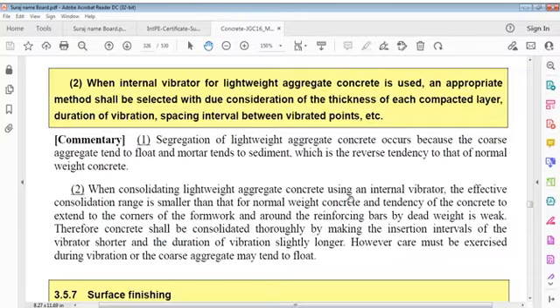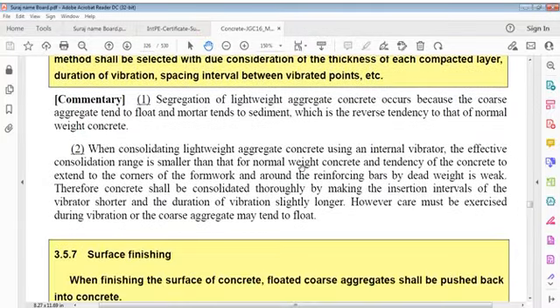When an internal vibrator for lightweight aggregate concrete is used, an appropriate method shall be selected with due consideration of the thickness of each compacted layer, duration of vibration, spacing, and interval between vibrated points. Segregation of lightweight aggregate concrete occurs because coarse aggregate tends to float and more mortar tends to sediment, which is the reverse tendency to that of normal weight concrete.